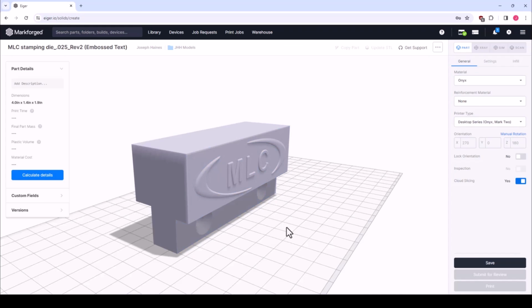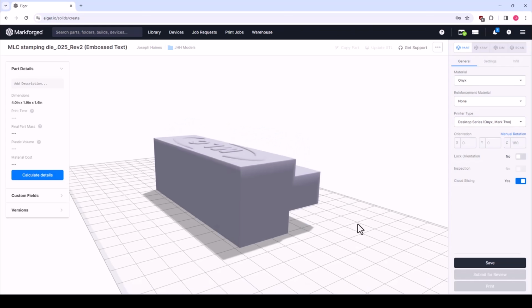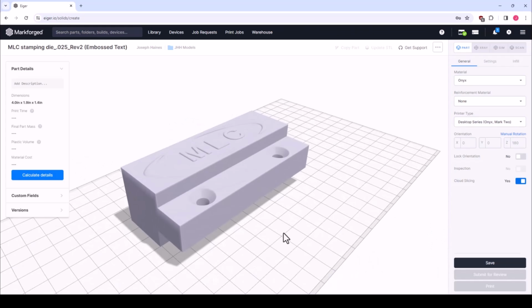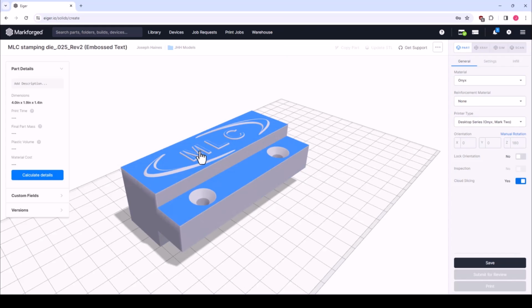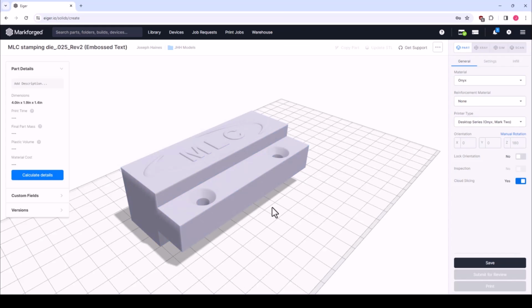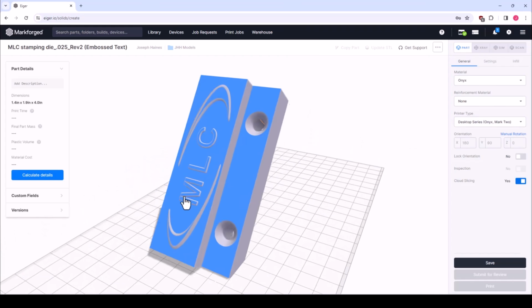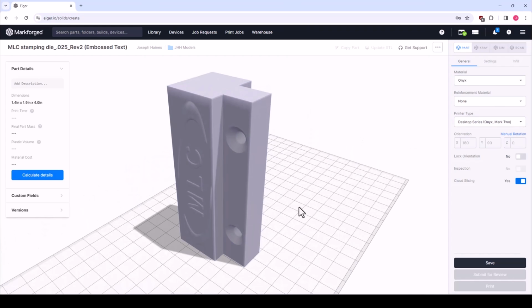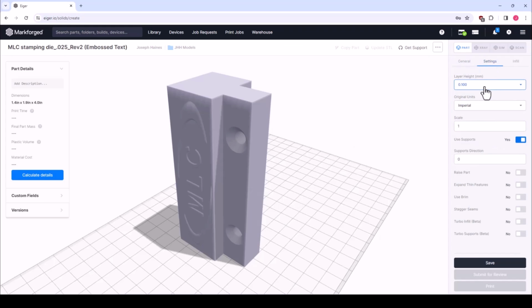Now for this die, there are two possible options here. However, only one is really the best. If I were to print it on this back face, the issue is how refined the logo will appear. I am at the mercy of the nozzle diameter in this orientation, which is 0.4 millimeters. If I instead print the part, say in this orientation, then I am at the mercy of the layer height, which, if I go into our little settings tab, is 0.1 millimeters. As a result, the logo resolution will be much better.